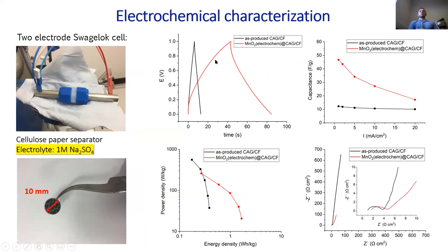So in this case, we can see after deposition of manganese oxide a significant increase of the area under the discharge curve, which translates into a pronounced increase of capacitance and the energy density of our system after deposition of pseudocapacitive elements. The impedance curves show that there is a slight increase of equivalent series resistance, which can be taken from the semicircle of our impedance curves, which also translates to a slight drop of the power density expected for pseudocapacitive materials.